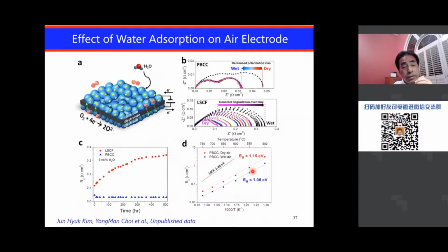Now, another interesting effect we have observed is that LSCF, one of the conventional or state-of-the-art cathode materials for solid oxide fuel cells, when you introduce a small amount of water vapor into the air, the impedance deteriorates very fast and quite significantly. So that's one of the problems with LSCF degradation.